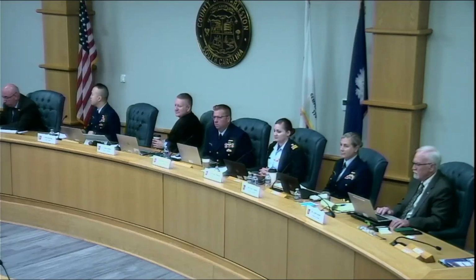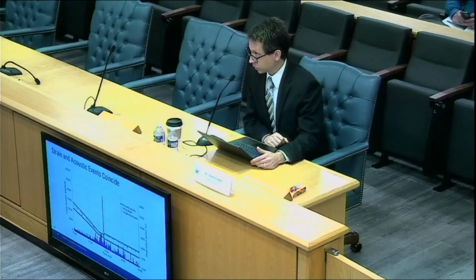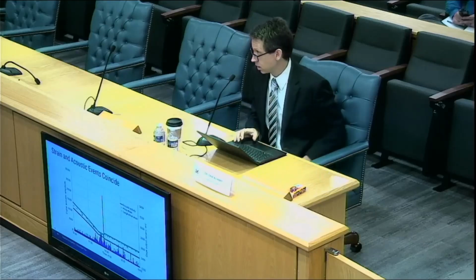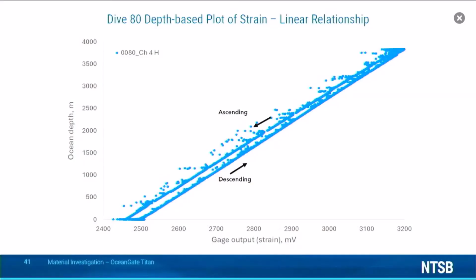All right, thank you. So referring to slide 40, when plotted together, one can see that the sudden change in strain gauge readout coincides with the large acoustic event. Some of the gauges showed a change in strain response after dive 80. OceanGate strain data was typically, and perhaps always, plotted as a function of time. The changes in mechanical response are easier to visualize by plotting the strain against dive depth, as shown here for the hoop strain at gauge group 4.